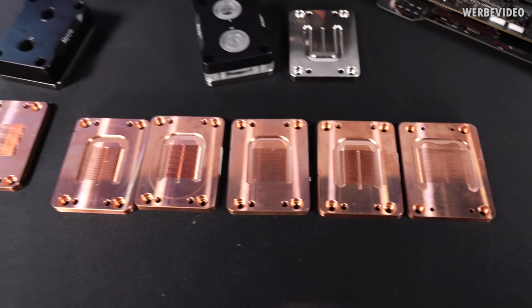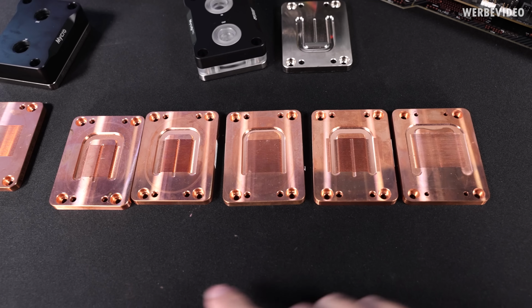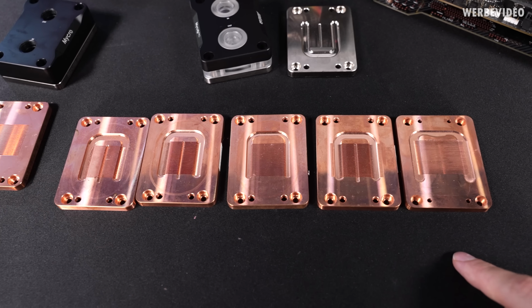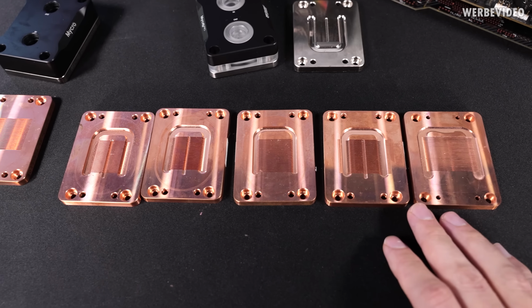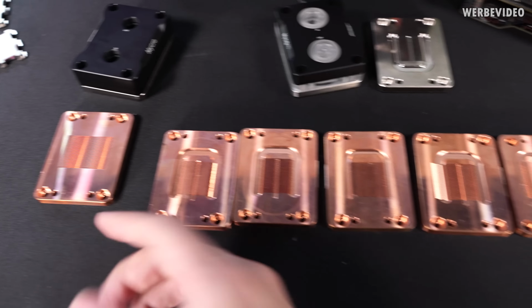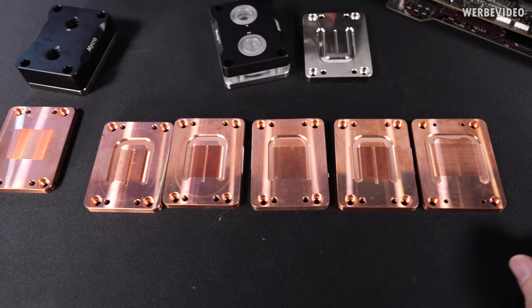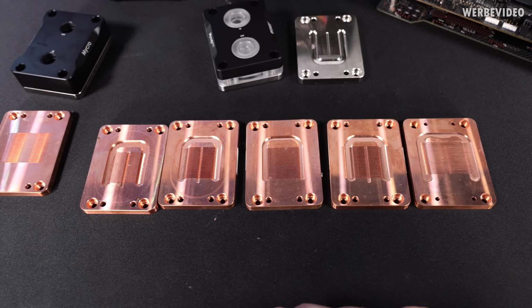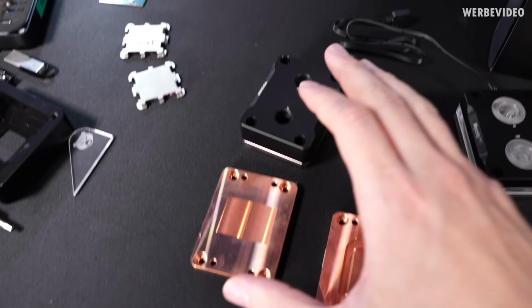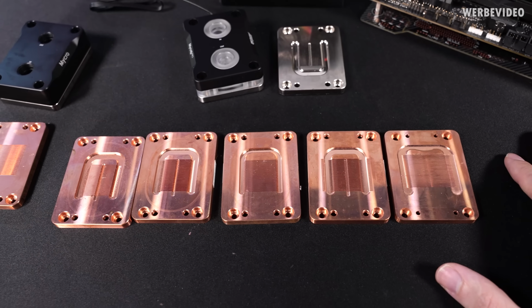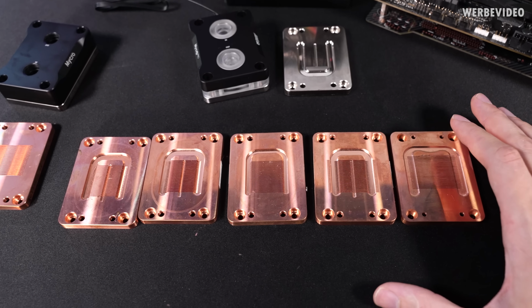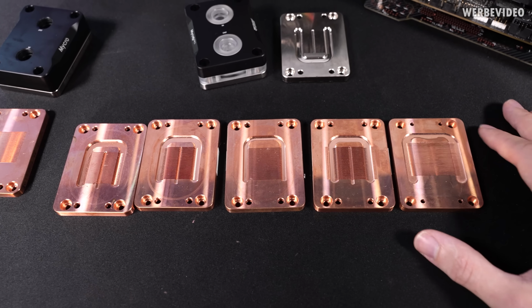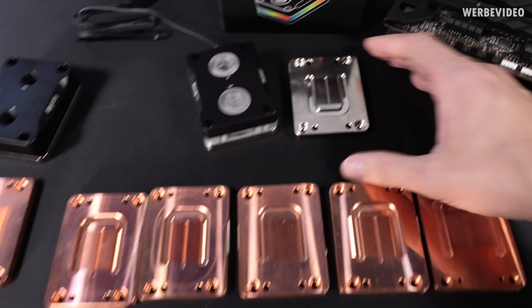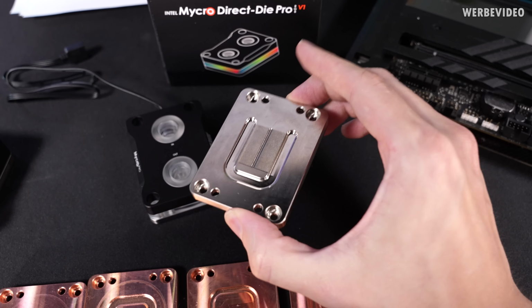And we figured out that we can make a much better structure. All of these are with 0.25 millimeter slotting. That means the surface area on these is potentially a lot better than on this one, and that also is much better for performance than the old block, which means we decided to just discontinue this product entirely and make a new one from scratch, have this with better performance, fix the nickel plating, and at the same time we improved the structure and the performance a lot. So that's the final cold plate, as you can see right here.